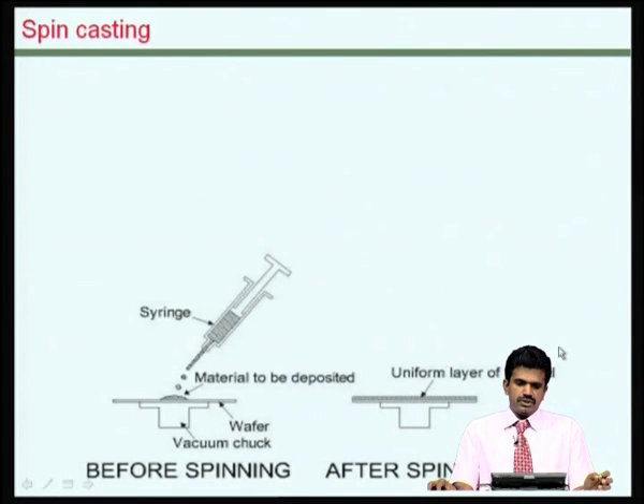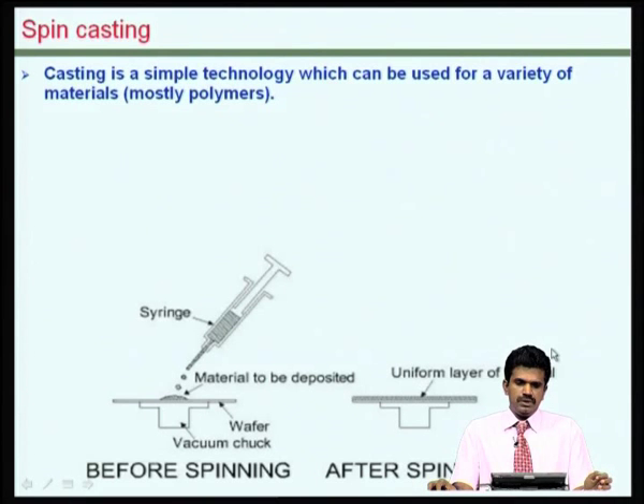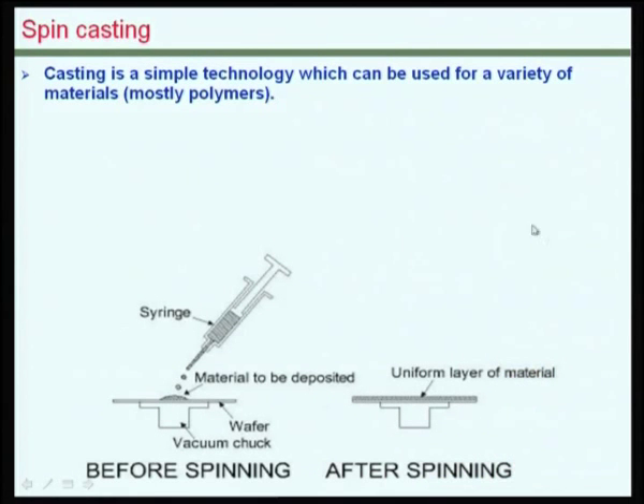Another simple scheme is based on spin casting or spin coating. This is typically used for polymeric materials including photoresist. What we have here is a wafer on a vacuum chuck which could be rotated, and what we do is we pour a few drops of the material to be deposited and then spin this at several thousand RPM under control, after holding it with the vacuum.